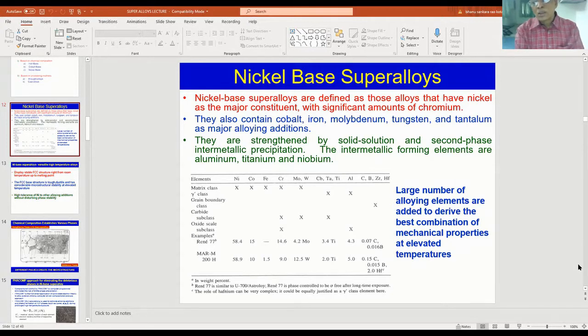iron, and both of these elements substitute nickel in the matrix, and they contribute to solid solution strengthening of the matrix. There are elements like molybdenum, tungsten, and tantalum as major alloying additions. These superalloys are strengthened by solid solution and second phase intermetallic precipitation.